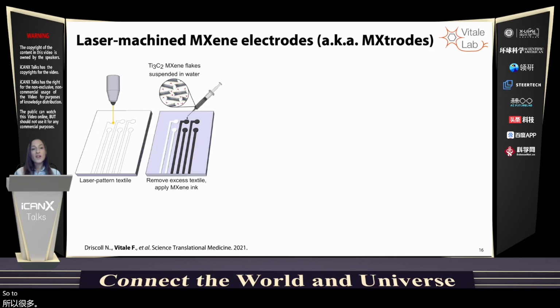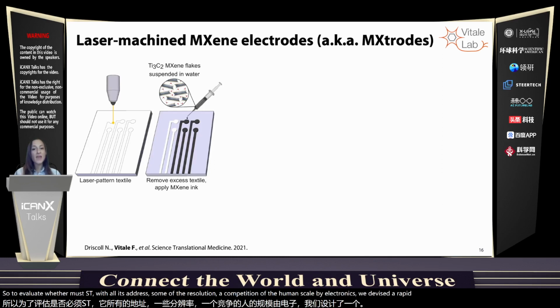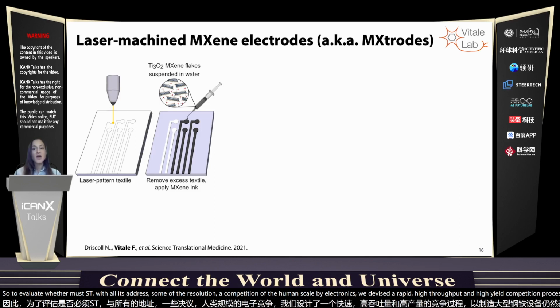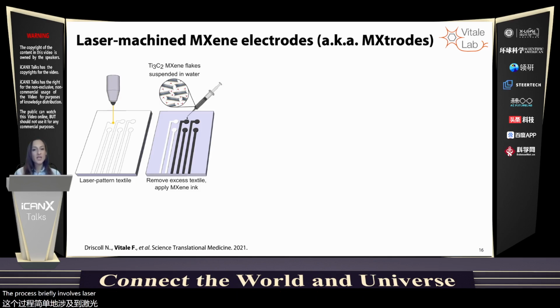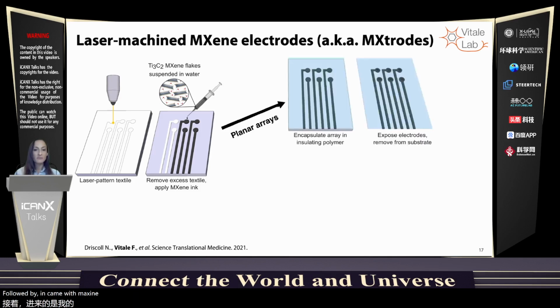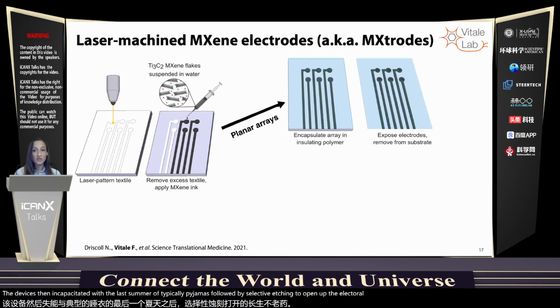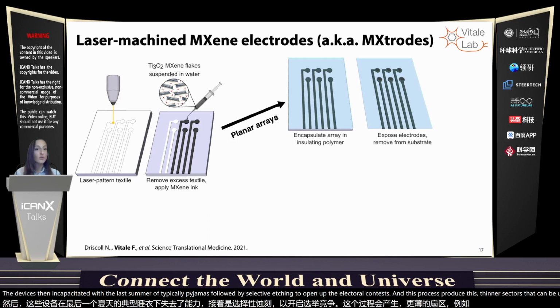So to evaluate whether MXene could also address some of the resolution and comfort issues of the human scale bioelectronics, we devised a rapid, high throughput, and high yield fabrication process for making large scale devices still based on MXene aqueous inks. The process briefly involves laser machining an absorbent substrate to create the electrode contacts, followed by inking with MXene. The device is then encapsulated with an elastomer, typically PDMS, followed by selective etching to open up the electrode contacts.